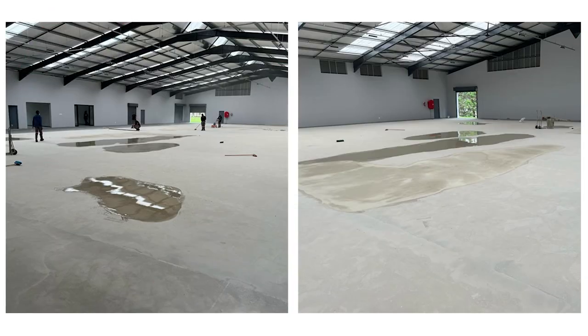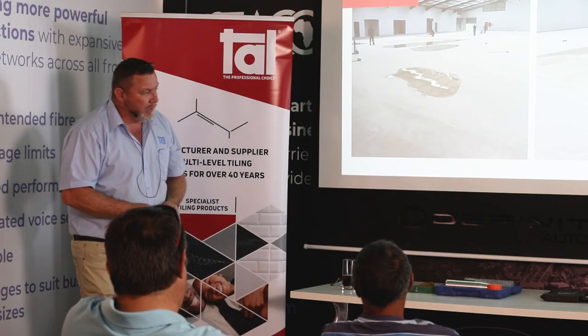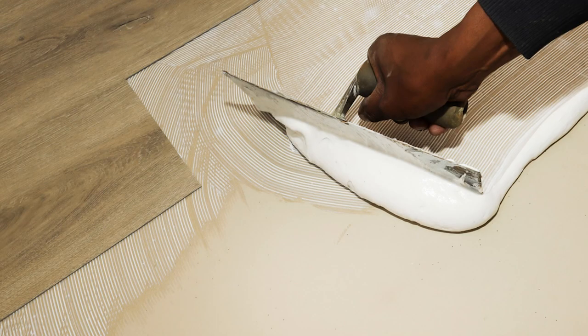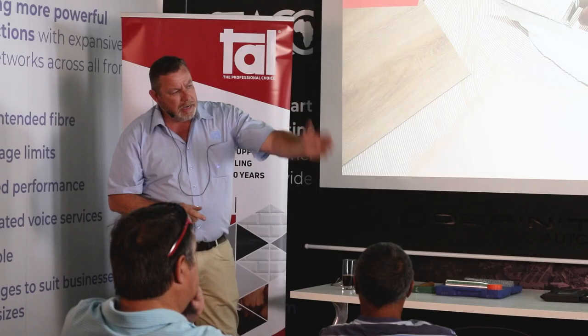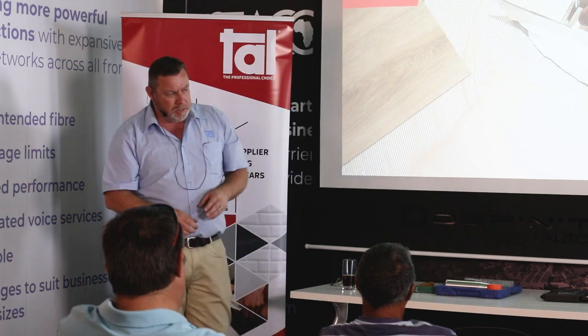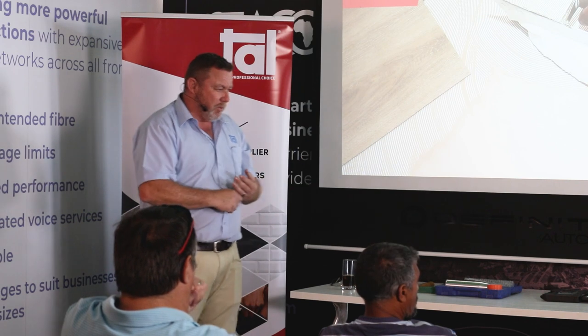If you do find lows, you have an opportunity to repair them. They've taken some self-leveling material, filled in the low areas, allowed that to dry, and then run a grinder over the surface to polish it up. Now that we've applied our primer or moisture barrier, we've applied a slurry to bond your self-leveling screed to the moisture barrier — because the two are natural enemies — so we need to marry the two together with either an aggregate or a slurry primer. Now we come to the adhesive.